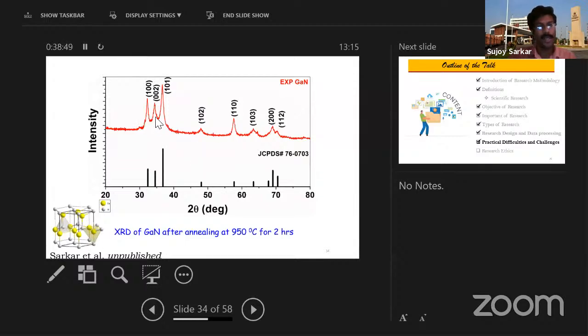But one thing you will find is that these peaks are broad compared to the known data, because the known data shows only a single line, which comes from a single crystal. Our material is not a single crystal, it's polycrystalline, and its size is nanometer scale. The crystallite size is so small that the peak becomes broadened. The peak is not very sharp like a single crystal. So if we analyze the data, we will find a lot of information from this. I just gave these two examples to give the flavor of this data analysis.